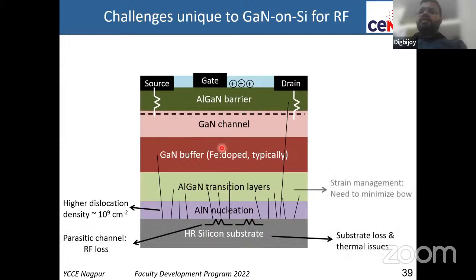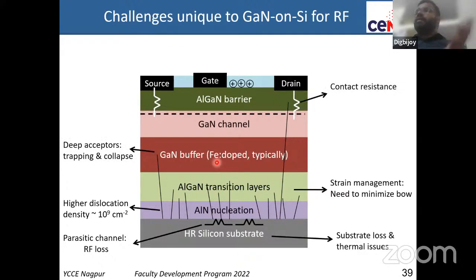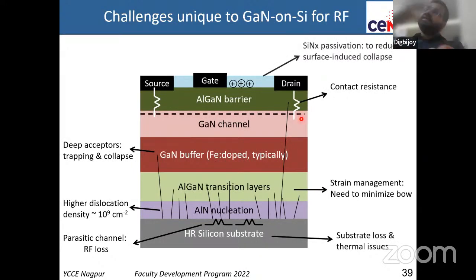Now, there are different things. One is the loss that has to be minimized. One is the strain that also has to be minimized, because you do not want a lot of bending and bowing in the layers. Contact resistance also has to be minimized, much better than in power electronics. In 600-volt devices, contact resistance can be a little bad, not a problem. But in RF devices, microwave devices, the contact resistance has to be super good, so that's very important. And one of the most important aspects is that your surface has to be protected by something like silicon nitride, because the defects and traps on the surface can lead to something called current collapse. When the current collapses, then you will not get any RF power. So that's an issue here.